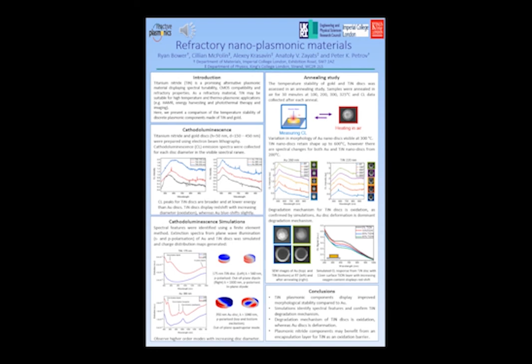However, there are spectral changes in both gold and titanium nitride from 200 degrees. So this indicates that there's a different degradation mechanism for titanium nitride, and we believe this is due to oxidation of the titanium nitride with annealing. We simulated this oxidation using a core shell structure, where we increased the amount of oxygen in a thin titanium oxynitride layer coating a titanium nitride core. And we observe redshifting and lowering of intensity of the cathodoluminescence response, which is what we see in the annealing study. So we can conclude that titanium nitride and gold have comparable temperature stability when patterned on the nanoscale when considering their optical response, but titanium nitride may perform better if encapsulated with an oxidation barrier. Thank you.